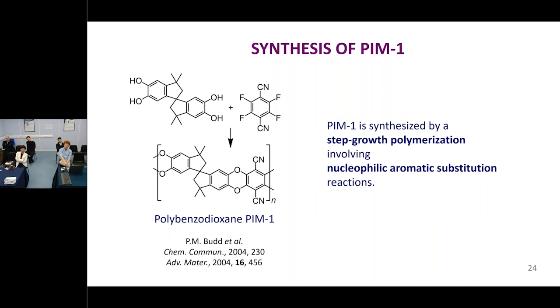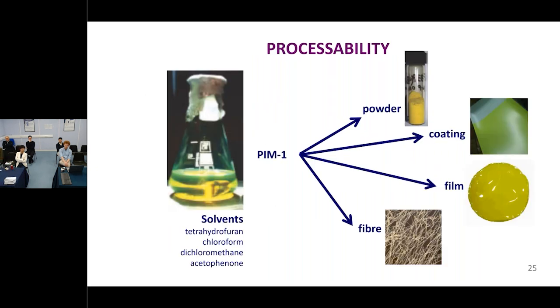And so you can see on the screen the idealized structure of PIM-1, which assumes your polymer is a continuous sequence of the repeat units that you can see there. And in a moment, I'll talk about why in reality that may not be the case. But the thing about this is it's a polymer we can dissolve in certain solvents. It's not always the nicest solvent, but we can dissolve it in things like tetrahydrofuran, chloroform, and such like, and therefore process it into powders. We can coat it onto surfaces. We can cast thin films just by letting the solvent evaporate. We can turn it into fibers by processes like electrospinning.